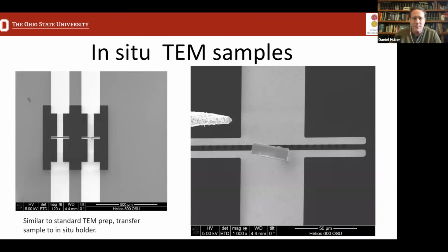We can also do in situ TEM experiments. So we have some in situ holders. We also use the DualBeam FIB for these purposes. So the technique that I do is I prepare a sample like I normally do, put it on the OmniProbe grid, thin it, we can even check it in the TEM. And then what we'll do is transfer the sample from the OmniProbe grid back onto the in situ holder.